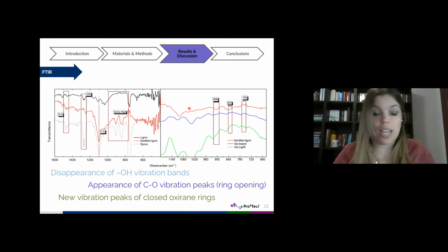between the hydroxyl groups contained in the lignocellulosic materials and the epoxy groups contained in the NADES formulation by the disappearance of these three peaks that we can see here in the green line. These bands are not present, are not shown in this spectrum. So the chemical cross-linking reaction has been done successfully.